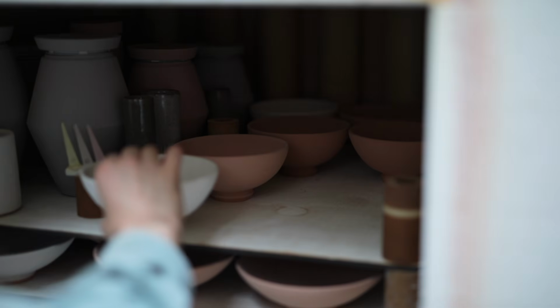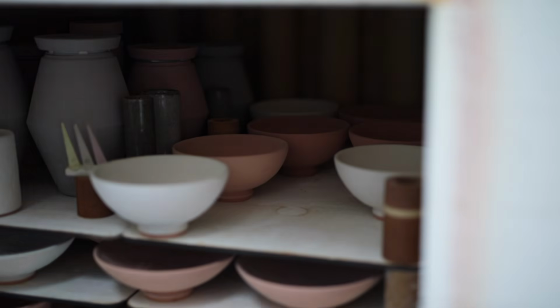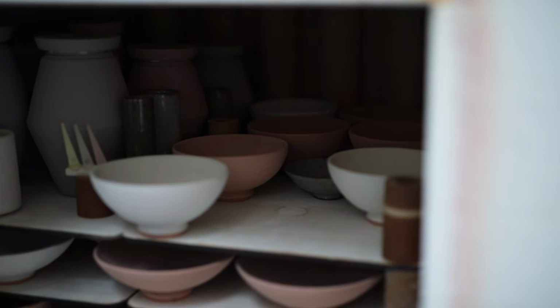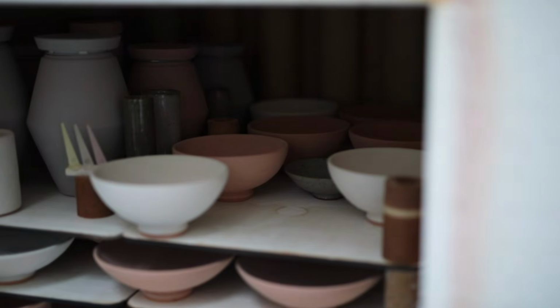On the left hand side of the screen, you can see 3 coloured spikes. These are called pyrometric cones, and each one is formulated to melt and bend over under its own weight at a very specific temperature. I can look at them during the firing through spy holes in the kiln's door, and it's these which really act as indicators to let me know when the firing is concluded, as opposed to the pyrometer, which simply reads whether the temperature is going up or down. These cones measure heat work, which is heat over time, and that's what pots need.